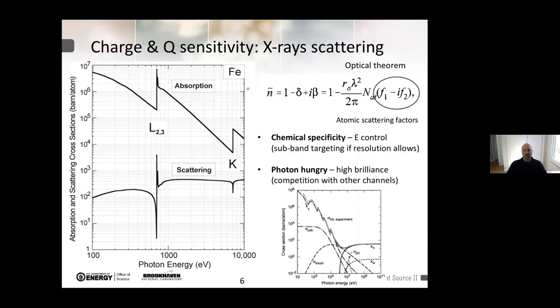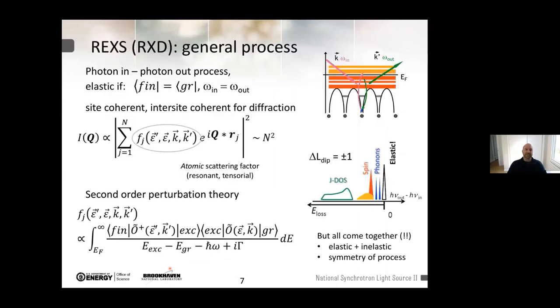And this is one of the cases taken as an example, but it's pretty much identical for everything. It's the case of iron. So you see very much that already just using photons, scattering is certainly orders of magnitude smaller than other phenomena, as is proved here on this logarithmic plot of absorption and scattering cross sections versus photon energy. However, there's hope, and in particular, what we want to do is to use a photon-in-photon-out technique that